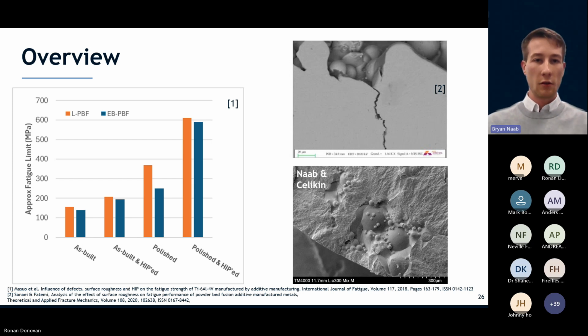And I'm just showing an image here of how a fatigue crack can initiate at a rough surface. The reason that fatigue cracks like to initiate at rough surfaces is because these little crevices act as stress concentrators, and then also loads on surface stresses are a lot more amplified than internal stresses as well, especially when you've got a component that experiences some bending component in the loading. And here is what an internal defect looks like, which caused fatigue. So we're looking at a fracture surface here, and we've identified that this is a defect which caused that failure.